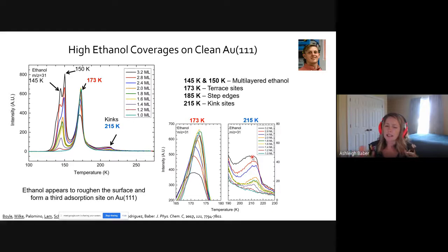And so we looked at data, we looked at literature that showed carbon monoxide bonded to gold step edges and kink sites, and looked at the energy of adsorption between kink sites and step edges. And that helped us arrive at this thought that this 215 Kelvin peak arises from the kink sites. The really weird thing is that this peak grows in intensity as we have more and more ethanol.